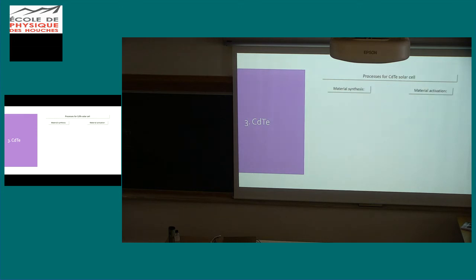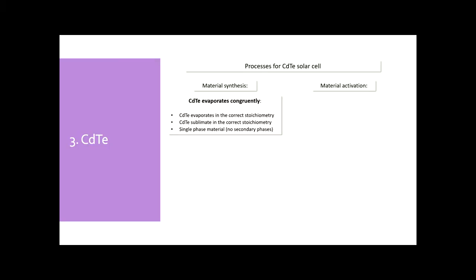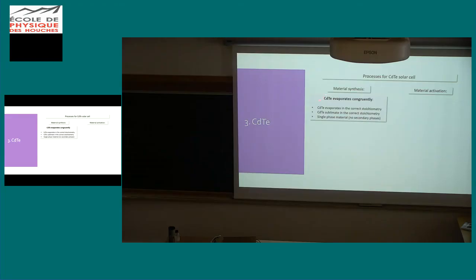You're welcome. So which processes do we need for cadmium telluride solar cells for the material synthesis? First, this is a general recommendation: when you start to look for a new material, always go first to the phase diagram, because the phase diagram could be your best friend or your worst enemy if you don't take a look before. And in cadmium telluride, we are very lucky because it evaporates congruently, in the stoichiometric relationship of atoms, and also sublimates with the correct stoichiometry.